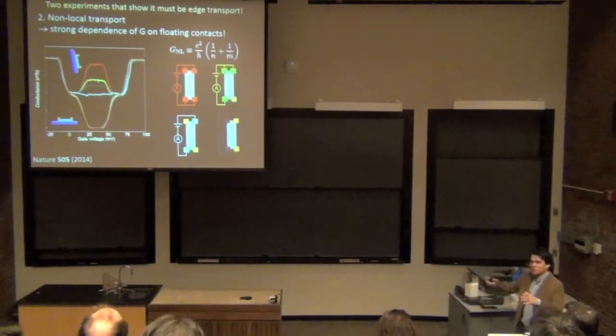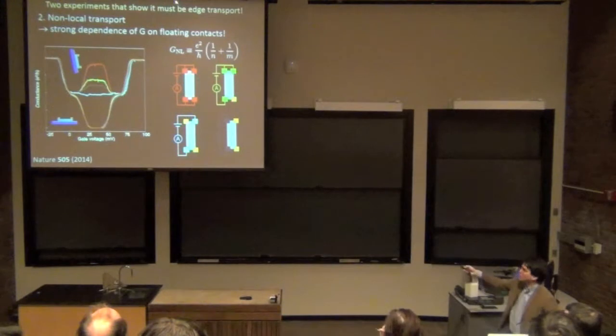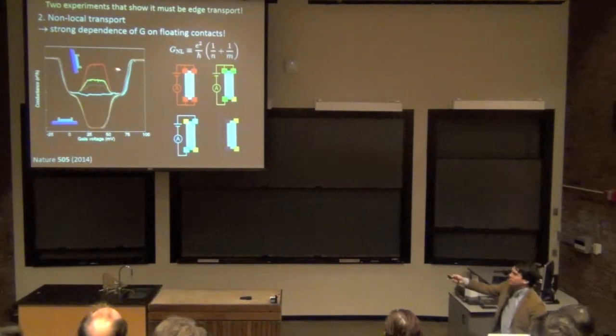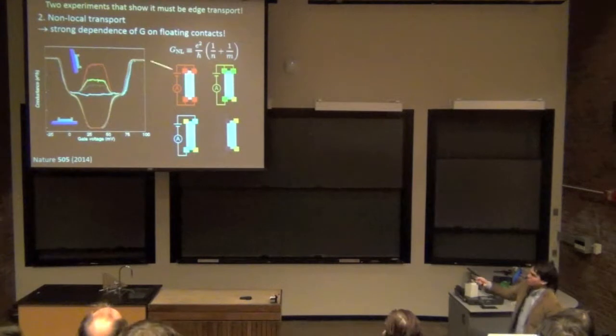So this is a pretty remarkable thing if you just think about conduction through a piece of metal, right? Imagine you have a piece of metal and you have four contacts on the corner, and you measure just between this edge and this edge, and then you remove two of the contacts, and you measure between one diagonal and one diagonal. There's no way you should expect to see a 50% decrease in the conductivity of that object, right? So this tells you that there is something interesting going on, and that interesting thing is that we're really seeing transport along the edges.